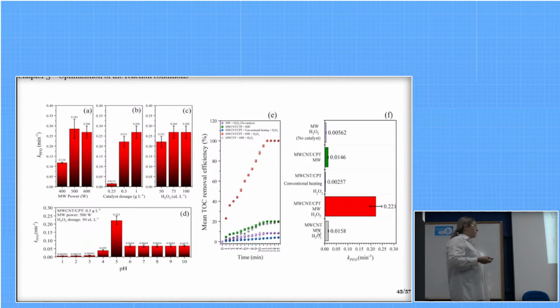We optimized the reaction conditions, testing the microwave power, the catalyst dosage, and hydrogen peroxide addition. The optimal condition was the use of 0.5 gram per liter of catalyst, a microwave power of 500 watts, even lower than the ones we tested before, and a hydrogen peroxide dosage of 50 milliliters per liter. With these conditions, we investigated the pH effect, and it was found that at pH 5, the kinetic rates increased much more than for any other pH value.